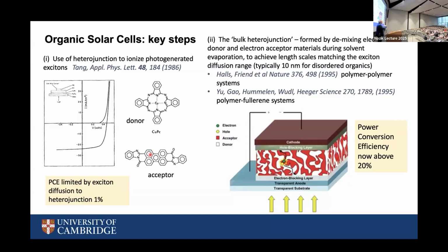And he showed very beautifully that this will work, but only when light is absorbed right at the interface, because the exciton has to be at the interface. So that was very, very influential. What has made it possible to get high efficiencies with organics is to turn that abrupt interface layer by layer into an interface everywhere by forming a bicontinuous network, an interdigitation of electron donor and electron acceptor.